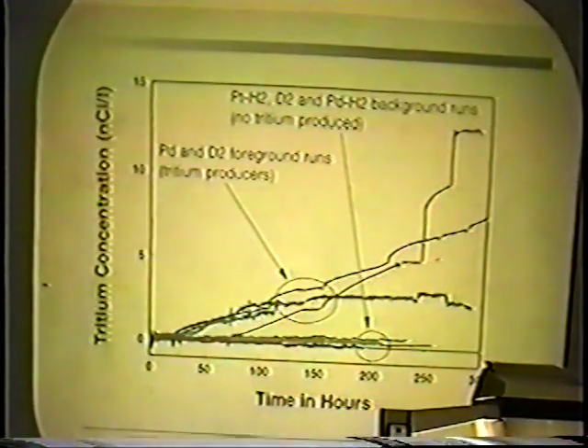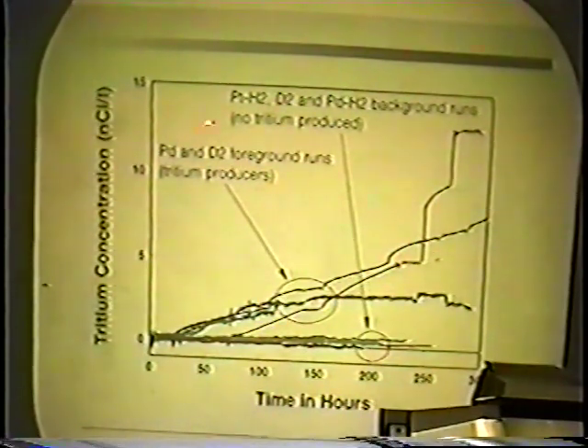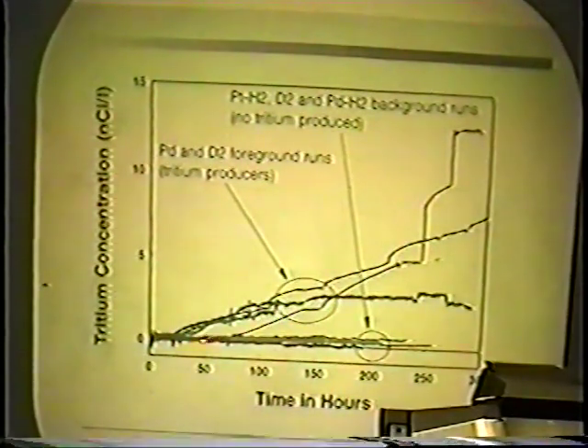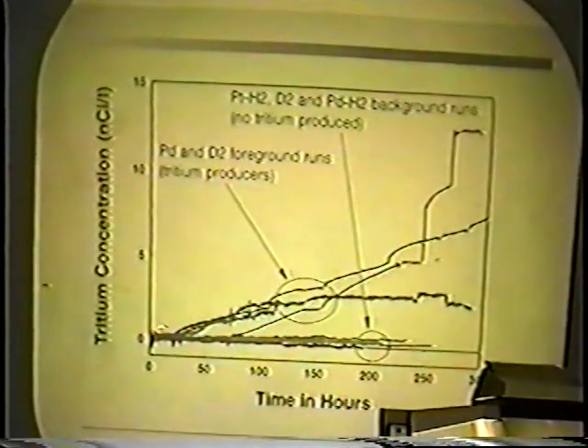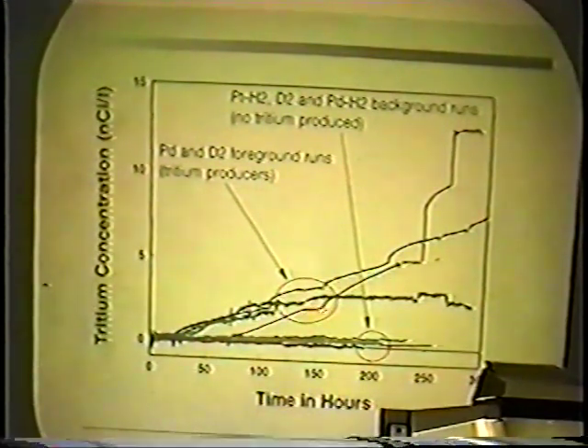These are some results that we had from last year. The colors really aren't coming out too well on this, but what you see are backgrounds here of platinum hydrogen, deuterium, platinum palladium hydrogen. These are all background runs which are just very close to the drift rate of the loop at that particular time. And these are palladium and deuterium foregrounds. And so what you see is when the plasma is switched on, you see a little glitch here, and then it starts to go up. Plasma's off here, goes up, plasma went off to there, goes back up, and the plasma's off there.